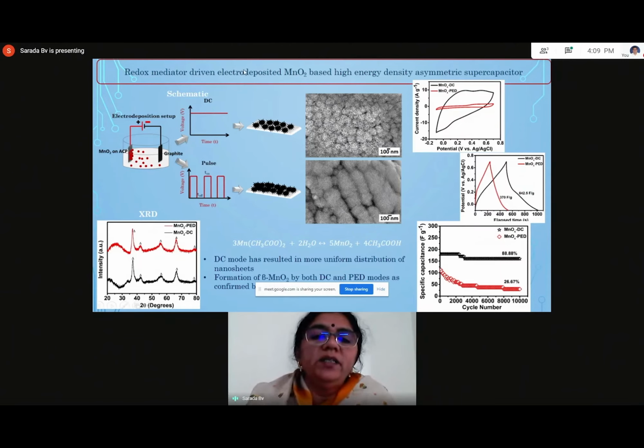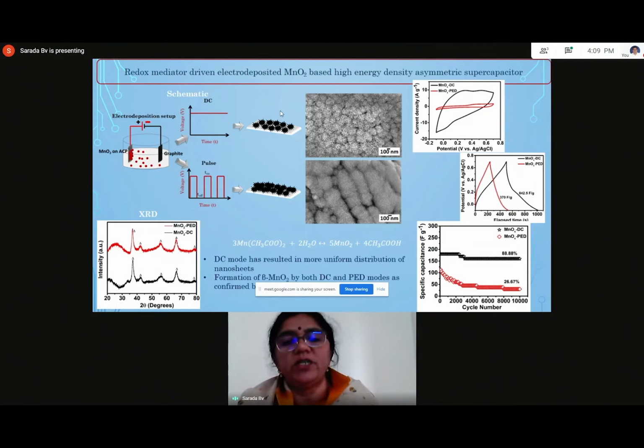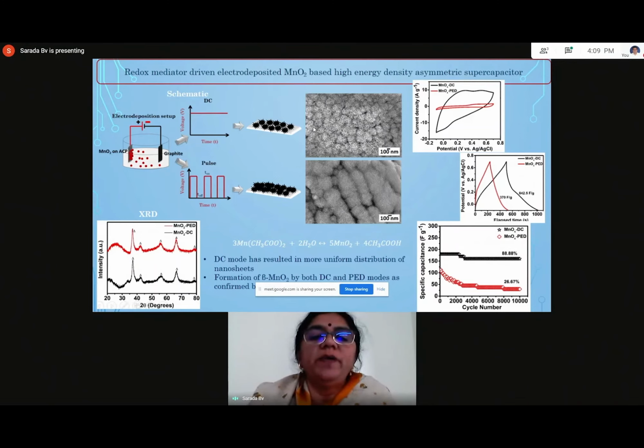Again, I was mentioning that you can improve the quality of deposition by using pulsed electrodeposition. However, in some of the processes, you can see that direct current deposition performs better, especially when you need very good porous nanostructures, because there is a very high current that is being given continuously. You can make nanostructures where during the deposition the hydrogen bubbles are formed, or in anodic deposition the oxygen bubbles are formed, and these create the nanostructures. But by sitting for a few seconds, they escape after the deposition and leave the nanostructures.